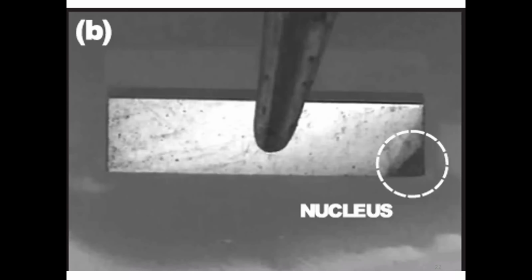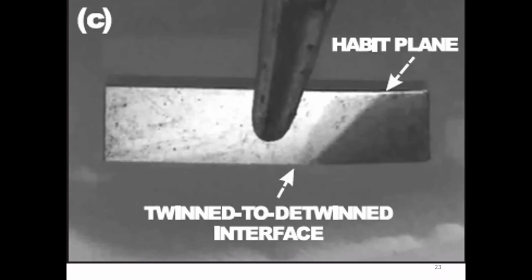Okay? And you'll see this in the movie, but I'm just showing you what to look for. And then you'll see a pair of interfaces that gradually eat up the whole domain. This part, the darker part, is the austenite. Okay, so here's the movie. But it shows dramatically how important compatibility is in these.